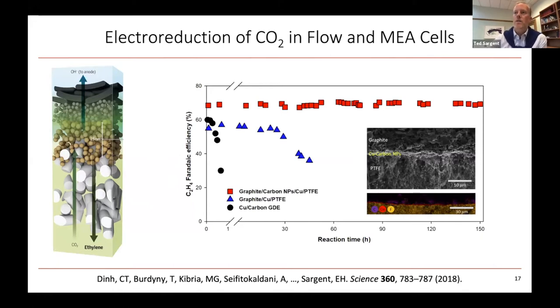A lot of the pioneering discovery of electrocatalysts had been done in H cells, so in aqueous solutions. But the challenge with that, of course, is that CO2 is not very soluble. And so we don't get a lot of productivity, we don't get a lot of current density inside those systems, and they don't offer a pathway because of the mass transport limits of CO2 at these low concentrations. They don't really offer a pathway to the kinds of activities that we need.